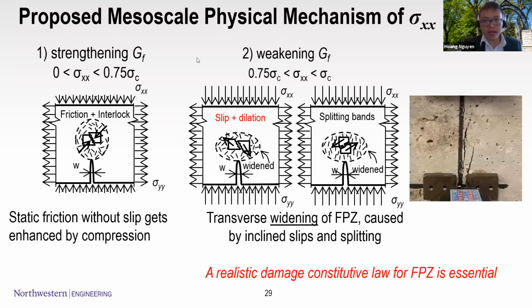So what mechanisms lead to that non-monotonic trend? We hypothesized that at the intermediate stress level there is a strengthening behavior. The strengthening comes from the high compressive normal stress, which increases the friction and interlock of the small and large aggregates within the concrete. When the material is separated by the bending moment, that interlock and friction increase the strength and the resistance against opening mode.